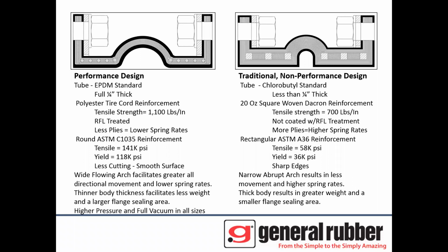It's more of a traditional non-performance design, and the body is very thick. You can see the thickness of the body is almost as tall as the arch height. So you have massive amounts of stiffness. So the movements are low, the stiffness is high. It's designed with square woven fabric with low carbon steel reinforcement, a narrow abrupt arch, and no coating on that fabric. So you could see delamination on these designs.